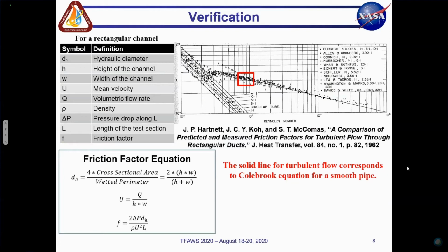So the first thing we did was go through a verification just to show that we can get reproducible data. Looking at Hartnett and some of the work that he did in previous years, he compared varying channel flow scenarios and the friction factors that they got, and how they were typically in line with the Colebrook equation itself. So we're able to calculate the hydraulic diameter and the height of the channel. We know the width of the channel. Using the area, we can get the mean velocity. We know density, we measure the pressure drop, and we know the length of the test section. So overall, we're able to calculate a friction factor from the measured pressure drop and volumetric flow rate.